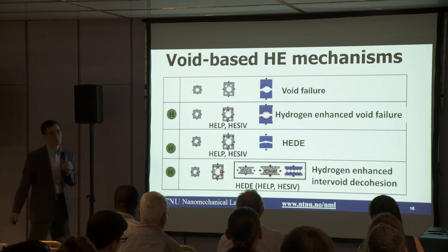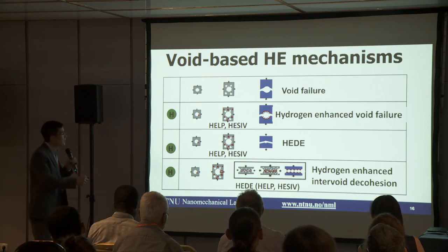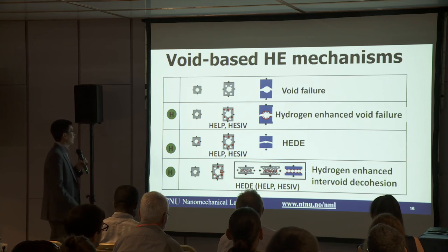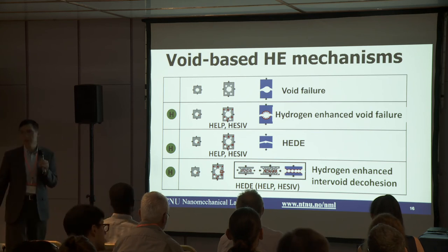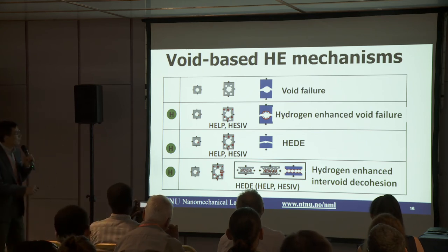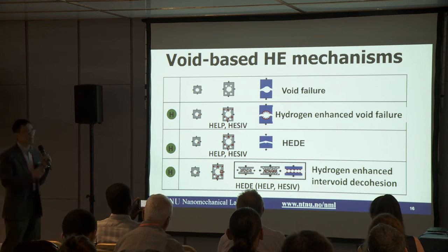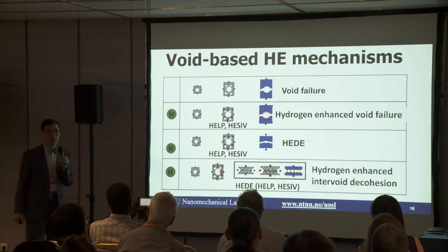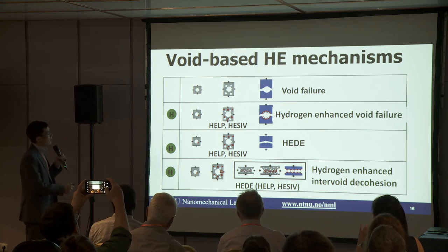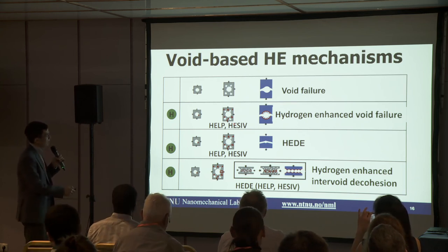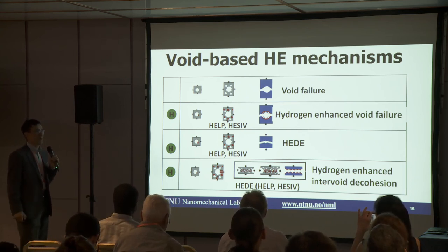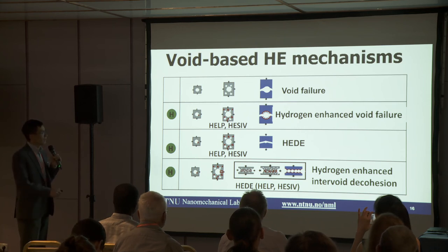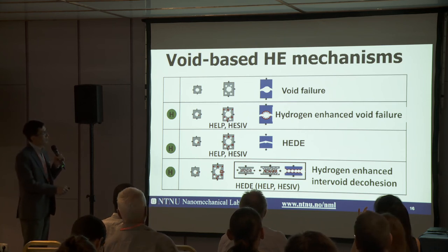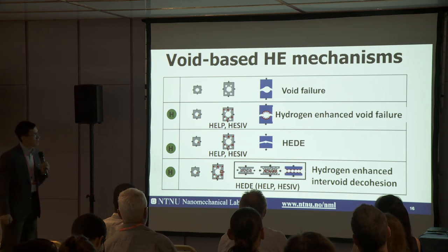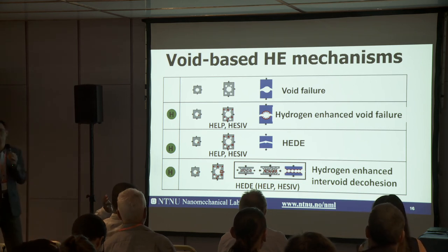We start with the ductile fracture, void failure, where there is void nucleation, growth, and coalescence. And with hydrogen, there is a possibility that maybe the initial void may be slightly influenced by the hydrogen. However, the growth and nucleation of voids will be greatly influenced by hydrogen. So we have a hydrogen-enhanced void failure.